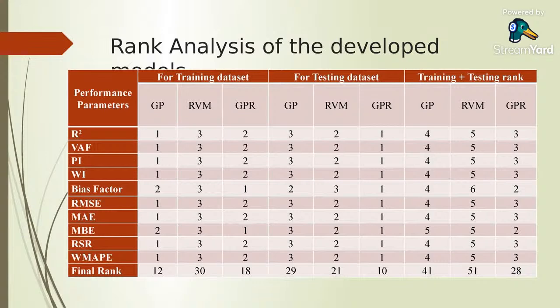The last analysis is rank analysis, which is very new and very efficient. From this rank analysis, we can see that RVM has achieved 30, whereas GPR 18 and GP 12. In testing, genetic programming achieved the rank of 29, followed by GPR at 10. From training and testing separately, we cannot conclude which is best: RVM is best in training, and GP is best in testing. But in the combined analysis, RVM is giving a rank of 51, whereas GP is giving a rank of 41, and the least performing model is GPR.